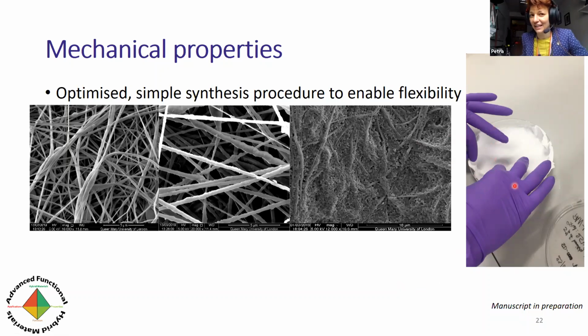The other thing is that you can see that it's quite a large area. She's got quite small hands, but at the same time, it's still 15 centimeters in diameter. And that is solely determined by the target size of the electrospinning. So this is a really upscalable method as well.